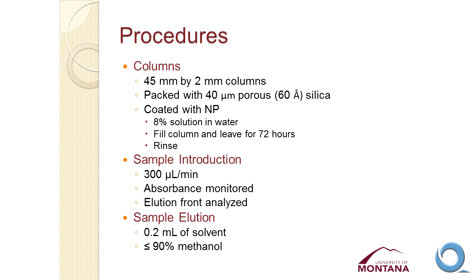All right, the columns we used here are 45 millimeters in length, 2 millimeters inside diameter. They were packed with 40 micrometer porous silica particles, bonded silica. They have a 60 angstrom pore size, and that's something to think about because the nanoparticles we think are nanometer scale, tens to hundreds of nanometers, so they would not immediately be able to get into those pores.